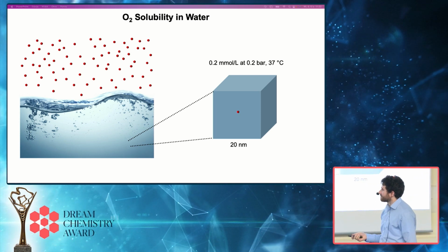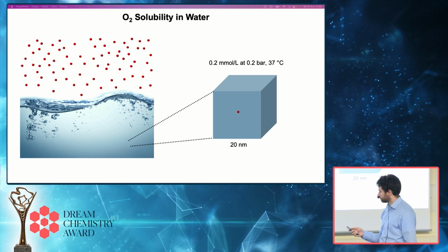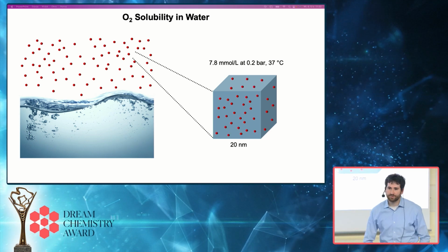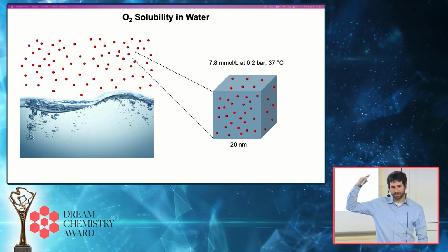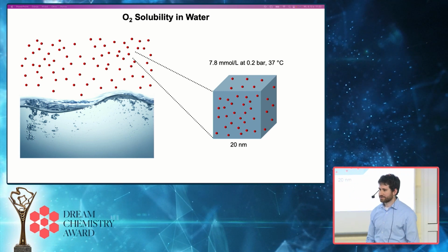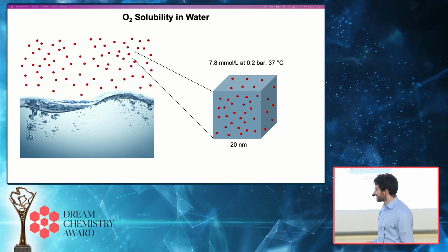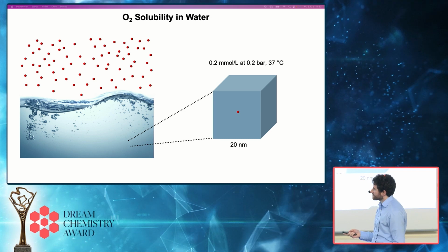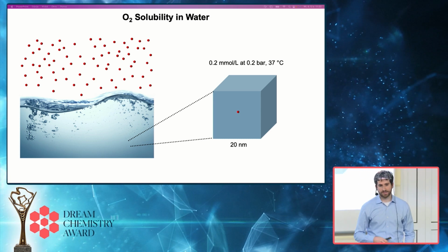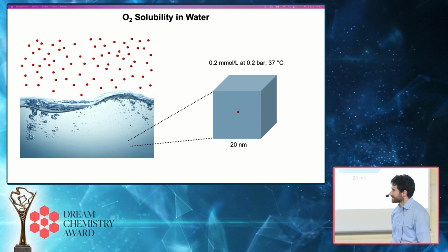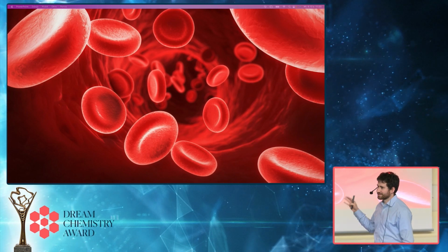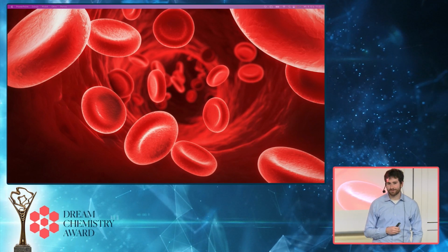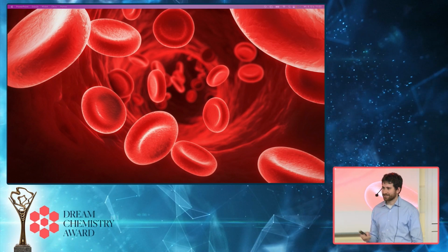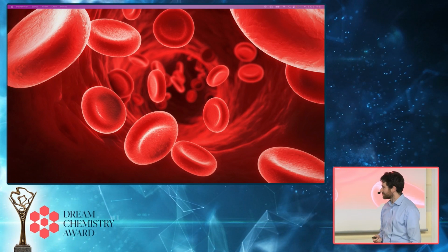The amount of oxygen that's present in water is about 40-fold less than the density of oxygen that's present in the air above it. So you have significantly more oxygen present in the gas phase. So this density of oxygen, of course, is not high enough to support life. And that's why over billions of years we evolved red blood cells and circulatory systems so that we can transport enough oxygen in order to be able to keep us alive.